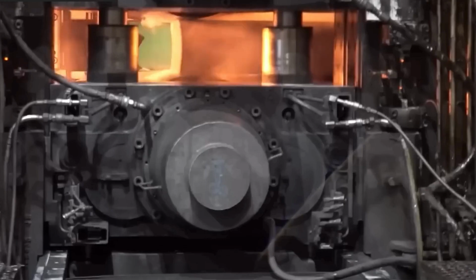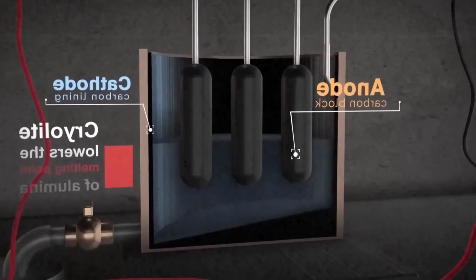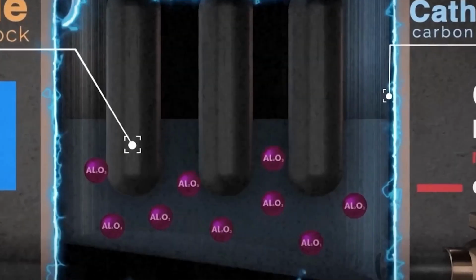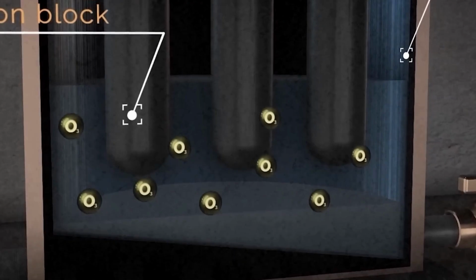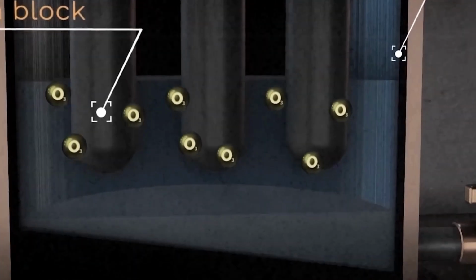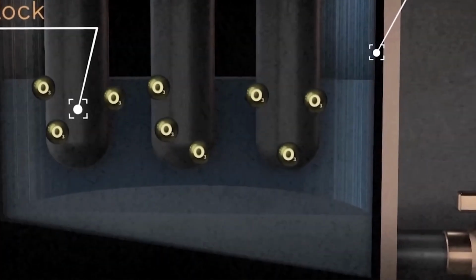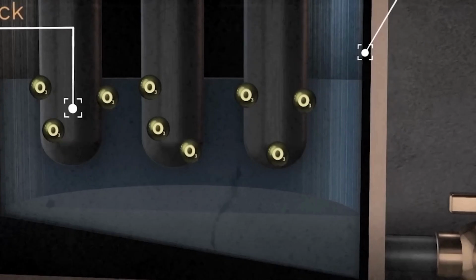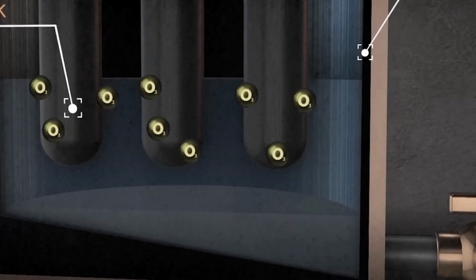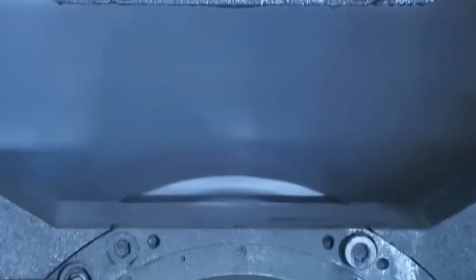This forms an electrolyte solution that enables electricity to flow from the carbon anodes above to the carbon-lined cathode at the bottom of the pot. As an electric current passes through the cryolite, a solid crust forms on the surface of the molten aluminum. Periodically, additional alumina is stirred into the mixture, breaking the crust and allowing it to dissolve.